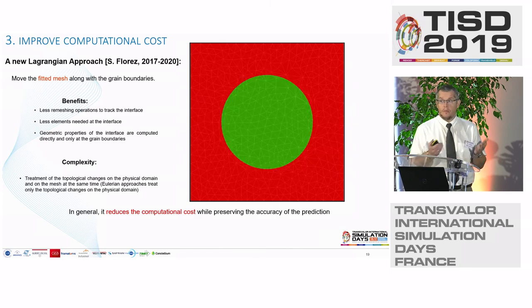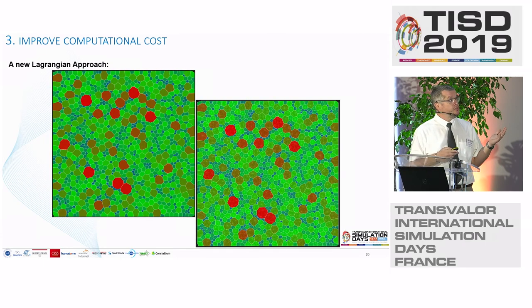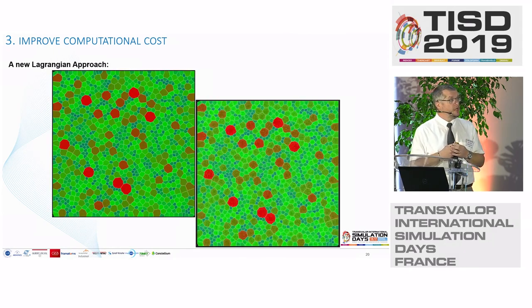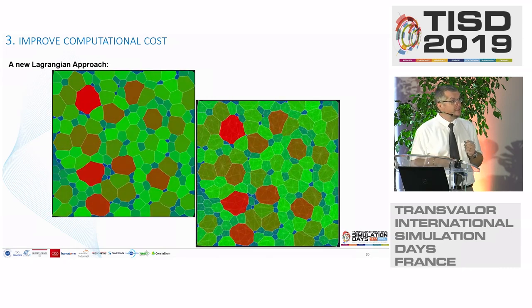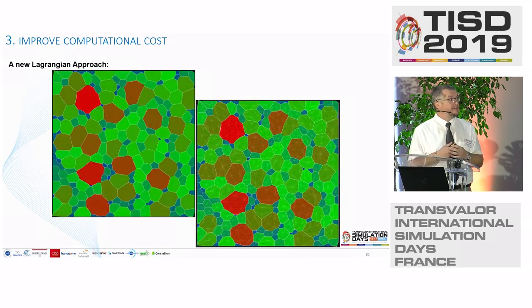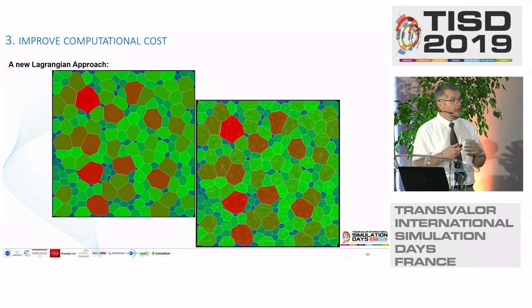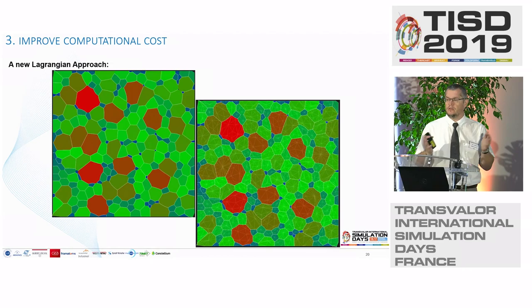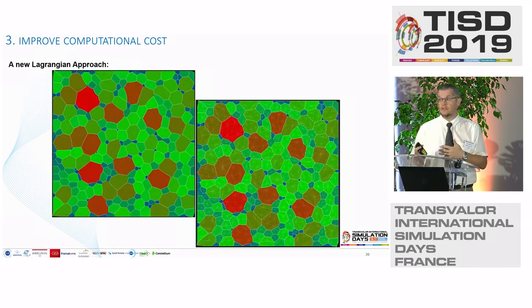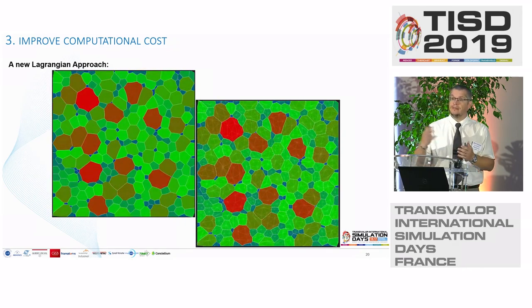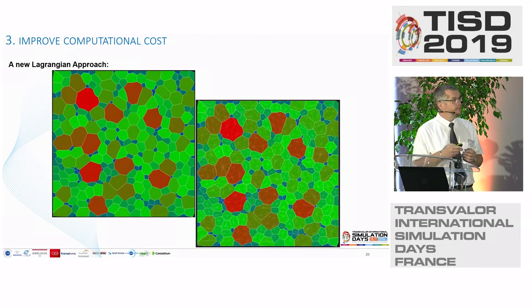We concluded that the current meshing and remeshing strategy is not the right approach to increase calculation speed by a factor of 10. What we are developing is to continue using the classical level set formulation but with a particular conformal Lagrangian description for grain boundary migration. This simulation was realized by one of our PhD students, Sebastián Flores. For a 2D grain growth simulation on stainless steel, we go approximately 50 times faster than the actual Digimu simulation with the same precision. It works in 2D today, and we are working to bring this to 3D in the next version of Digimu.